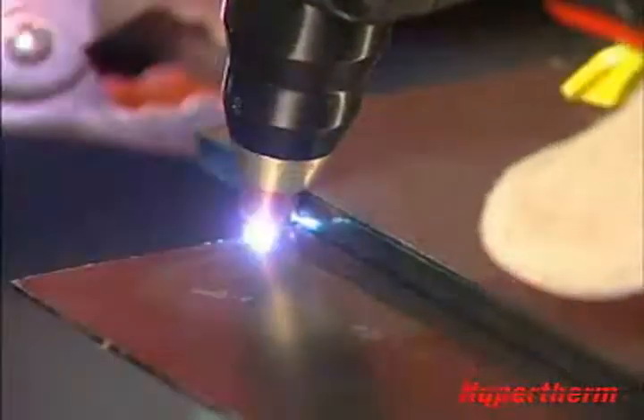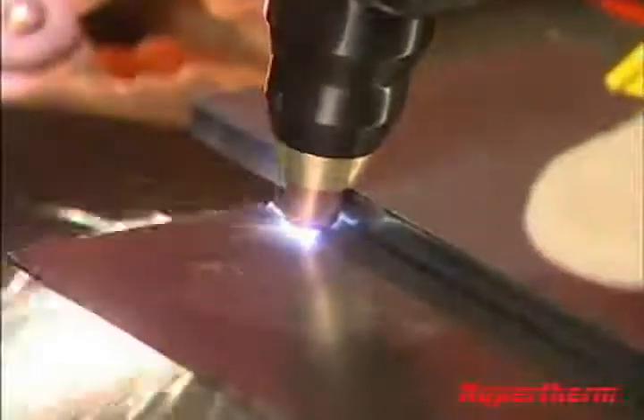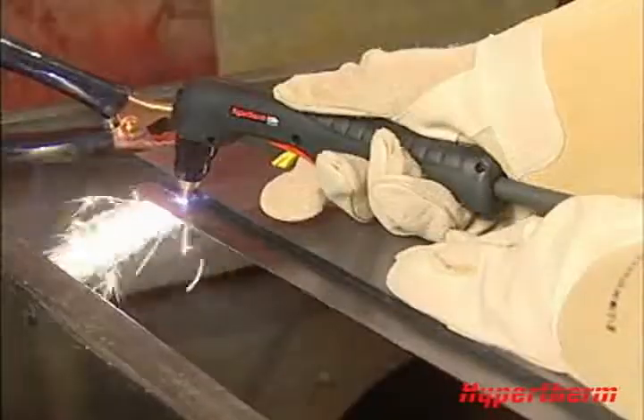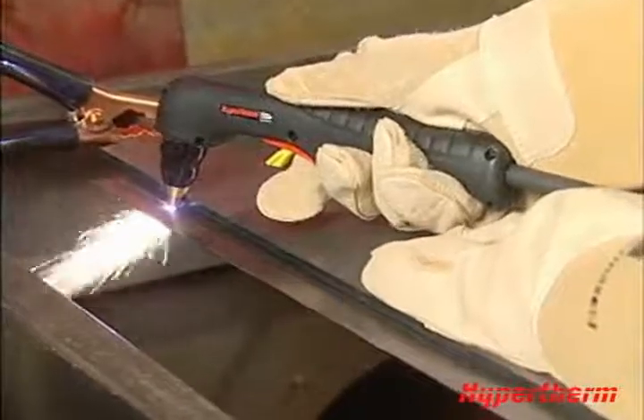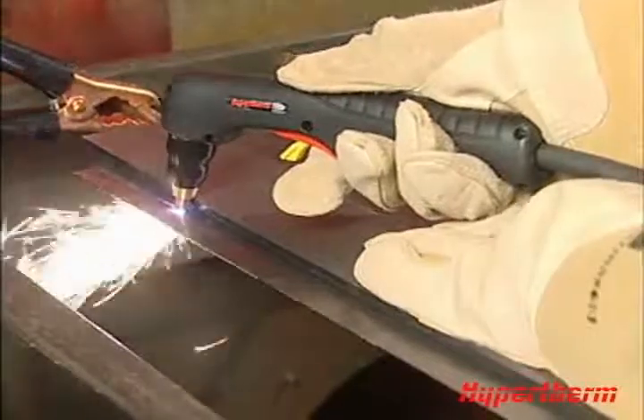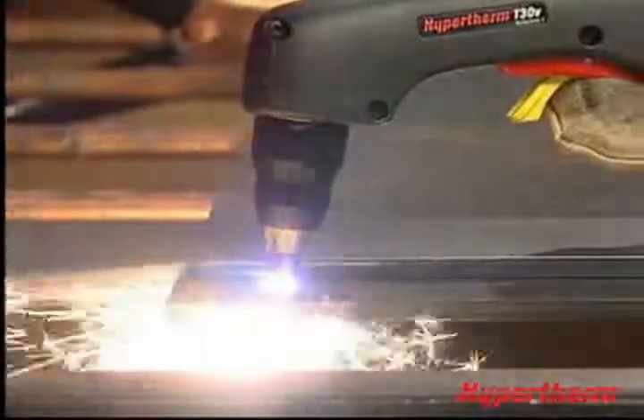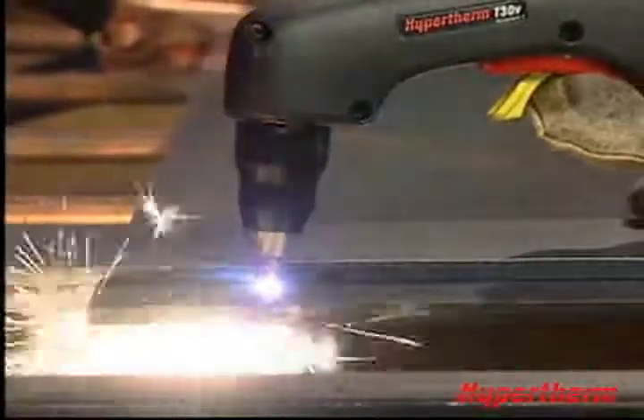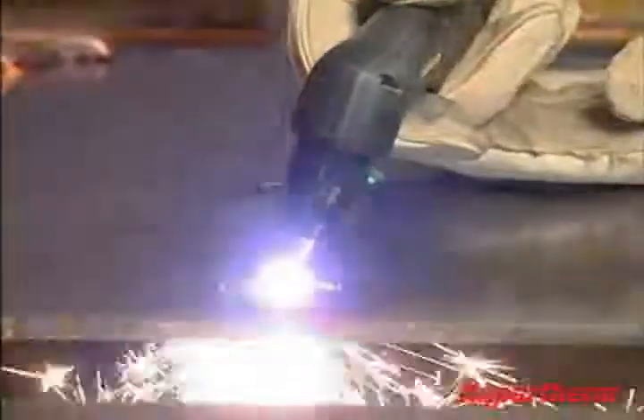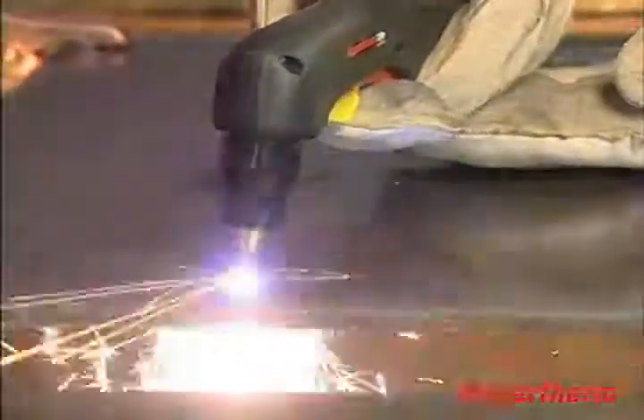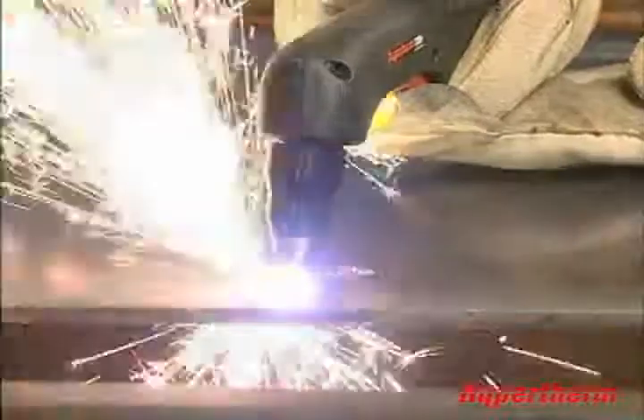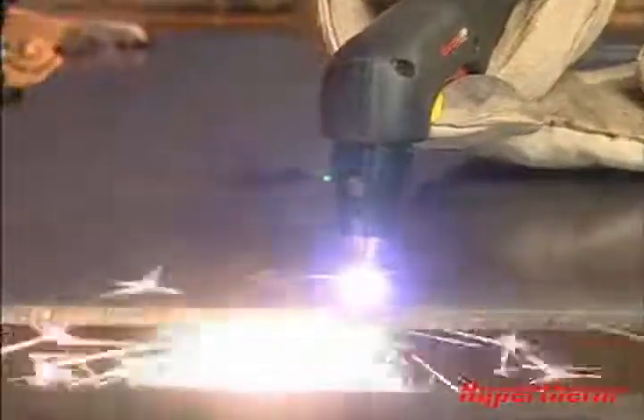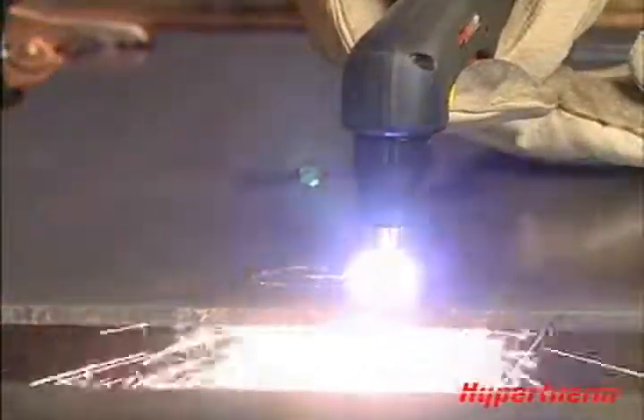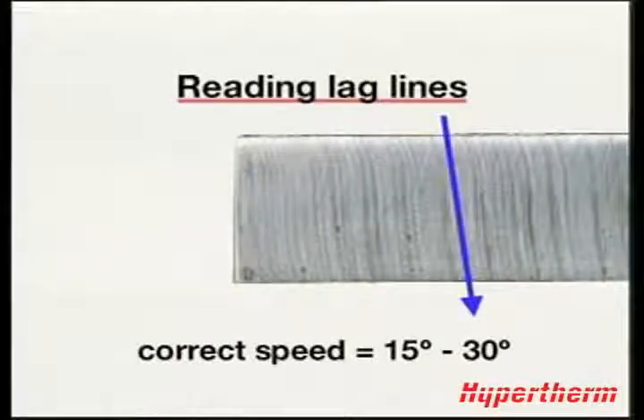Maintaining proper travel speed is key to successful cutting. Watch the arc beneath the plate, as sparks should lag 15 to 30 degrees behind the cut. If the sparks are vertical, then you're moving the torch too slowly. If the sparks are perpendicular to the cut, or are spraying up from the workpiece, you're moving too fast or don't have sufficient power. Lag lines on finished cut edge should also be about 15 to 30 degrees.